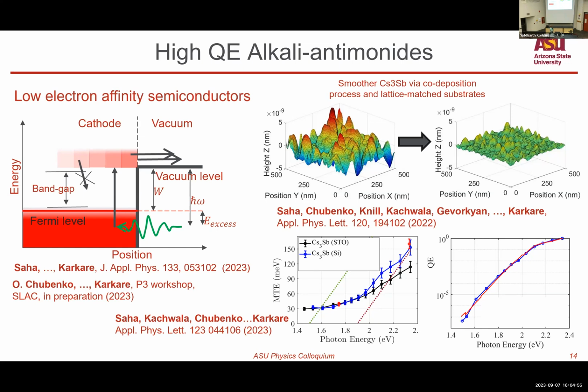And if you are willing to compromise a little bit on the mean transverse energy, you can get a large 10 to the -3 level quantum efficiency, which is many, many orders of magnitude higher than a metal. And we demonstrated a sub 50 milli-electron volt mean transverse energy with a 10 to the -3 quantum efficiency, which is again an order of magnitude smaller than the 500 milli-electron volts that's being used today. And now these cathodes are being considered for the next X-ray free electron laser, the LCLS-II high energy upgrade that SLAC is building.